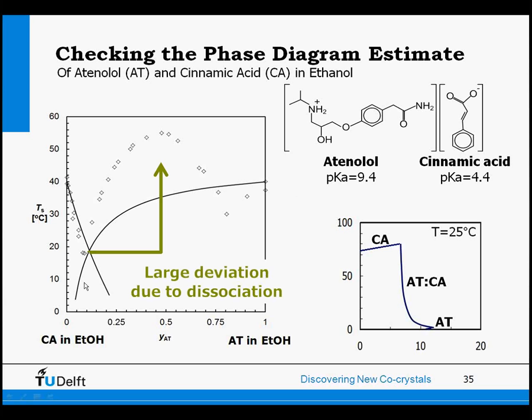If you look at the pure component solubilities, you would want to screen here at the point where these two solid lines cross. But if we determine this diagram, you see that you have the largest possibility around the 1-to-1 stoichiometric solutions. But that is for compounds that dissociate due to the presence of another compound.